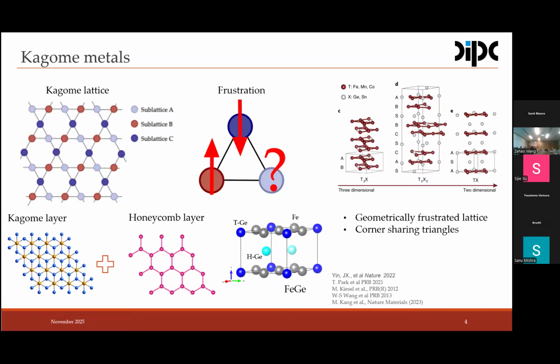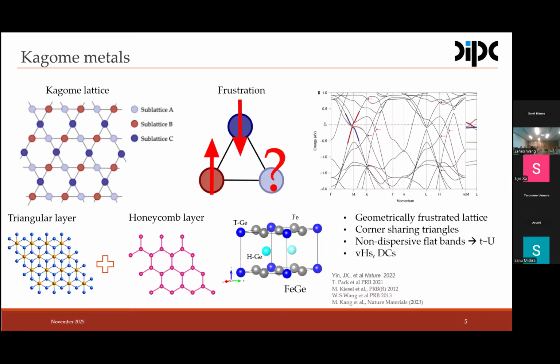From the electronic point of view, these materials are becoming a very hot topic, and the reason is that they host flat bands and van Hove singularities. Flat bands are in the reciprocal space, and van Hove singularities are at the M point and the Dirac crossings at the K point. So this geometrically frustrated lattice, together with these electronic features in the band structure, is very important to study correlated phenomena, like charge density waves, static magnetism, or even superconductivity.